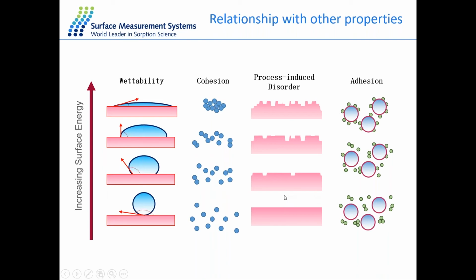Because we can inject multiple concentrations, we can have an understanding of the heterogeneity or the homogeneity of the surface of the sample. So if you have any defects or surface porosity, it's useful for analyzing these surfaces. We can also calculate work of adhesion. This is for unlike materials, where you wish to calculate the work of adhesion between the two.